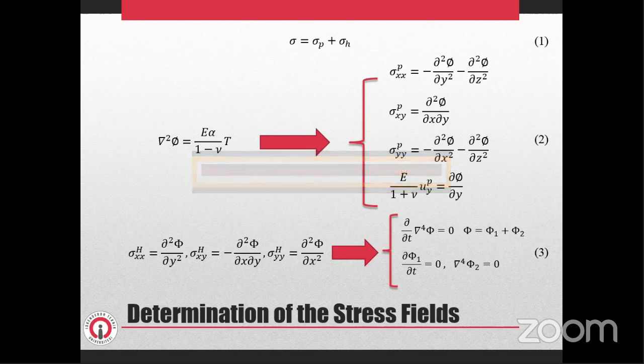Incompatible strains don't change as a function of time, because we assume that no inelastic strains can occur at any point of the solid after it has solidified. Therefore, Airy's stress function has the following form in the right part of equation 3. The general solution of this equation can be written in two parts, where Φ1 and Φ2 denote residual stress and the instantaneous stable response of the solid to the varying temperature field.